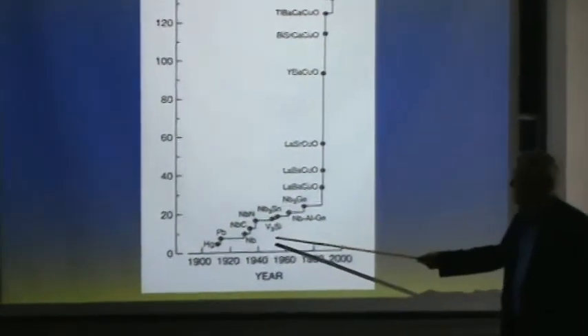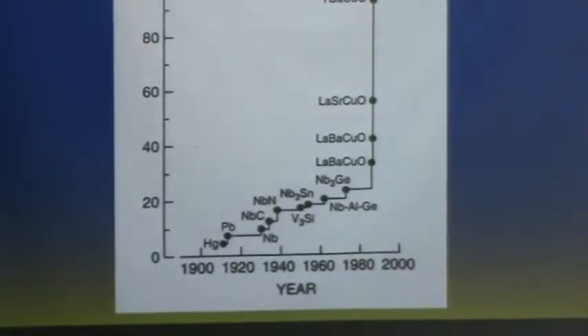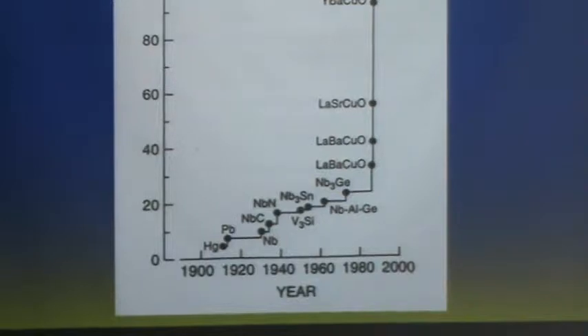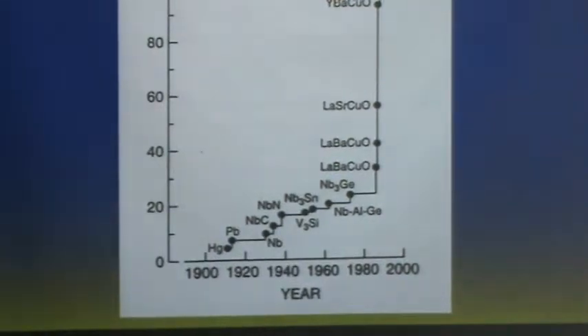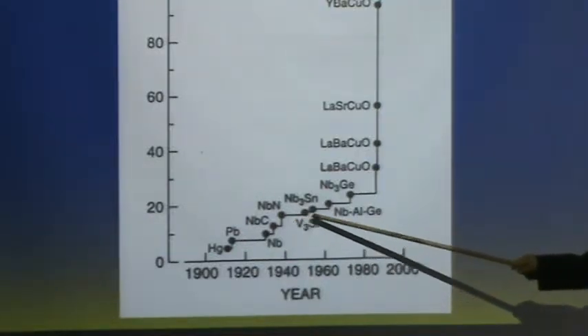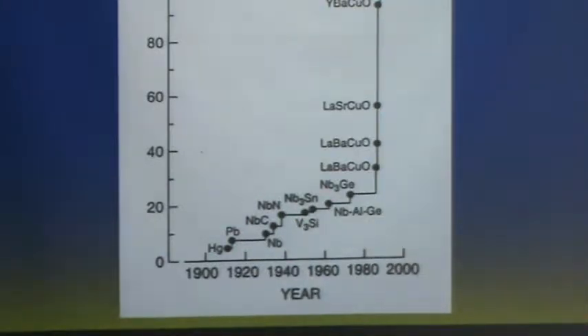And then someone looked at niobium, and they discovered that by looking at niobium-type materials, so these are 4D transition metal materials, they were able to progressively, by good material science, increase the superconducting transition temperature. And they got it up to about 20 degrees Kelvin. And niobium wires are the basis of most of the large-scale practical applications of superconductivity still.